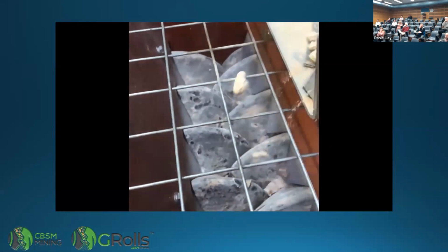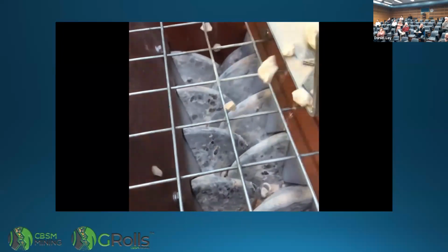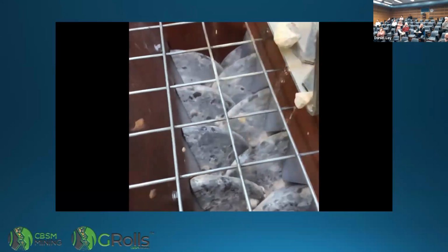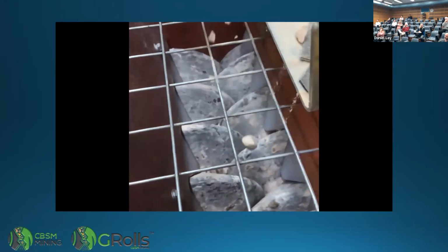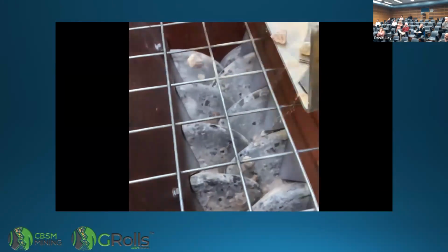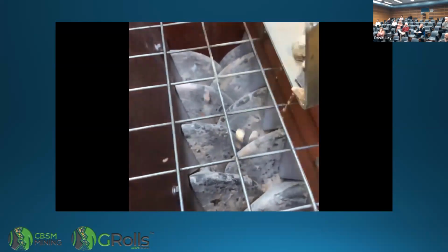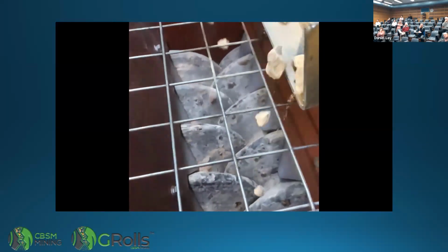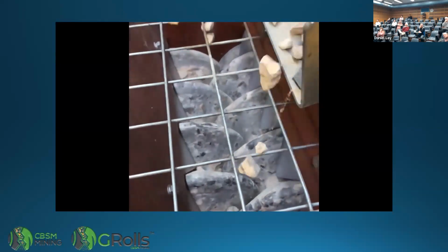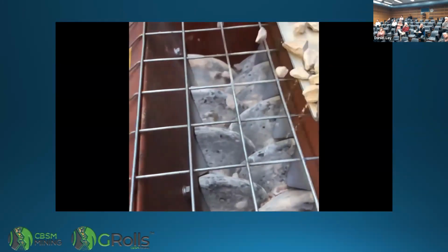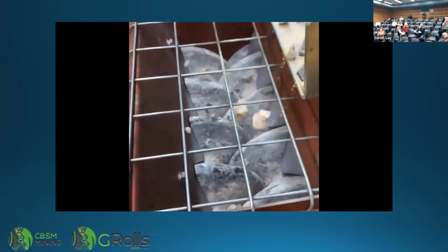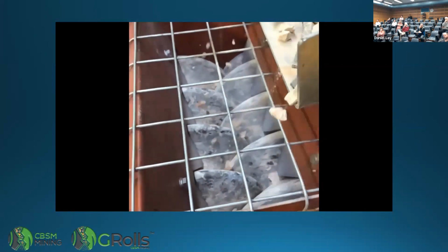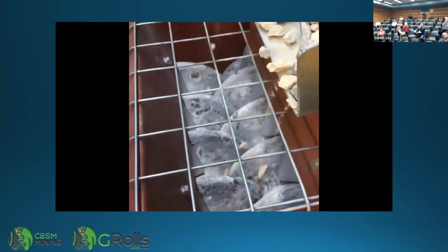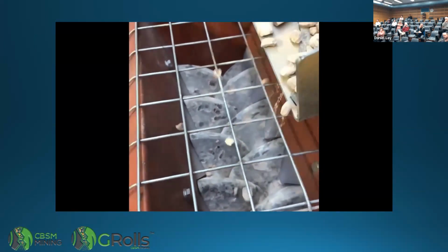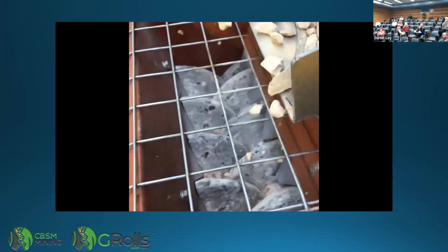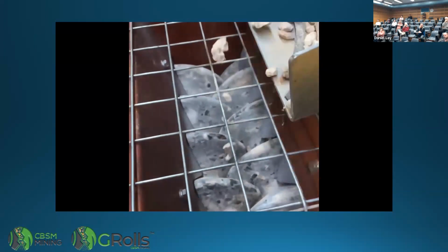So this is 20 mil, and you can see that it's going into the crusher, and there are all different little crushing chambers in there, and you can see the material getting compressed into those pinch points. So that's what happens in a coarse material. When you do a fine material, you have more material on those surfaces doing shear. With coarse material, you're more probably doing compression. And so, yeah, it looks like brute force.